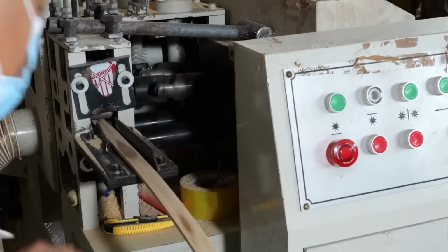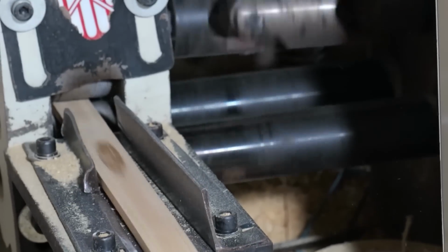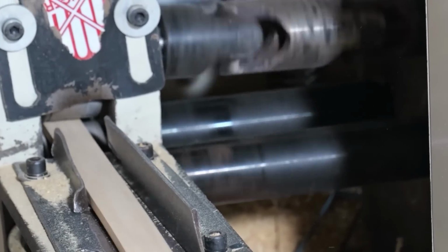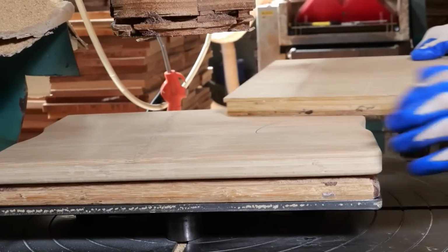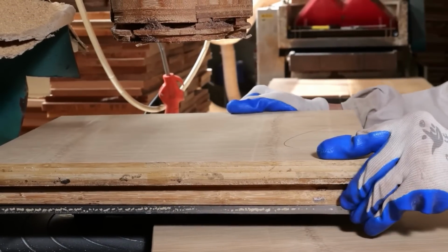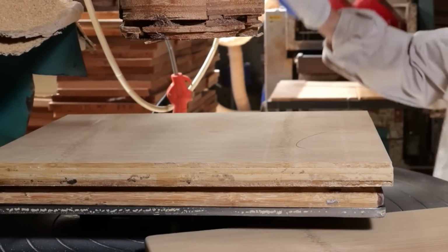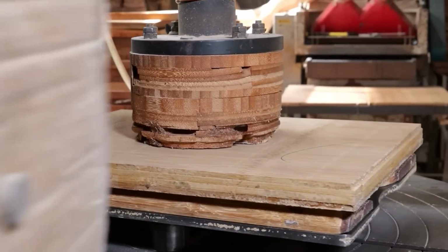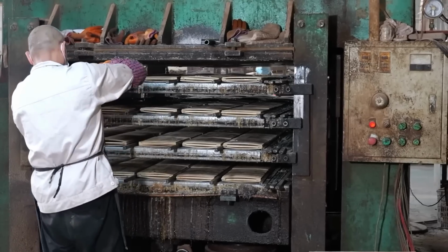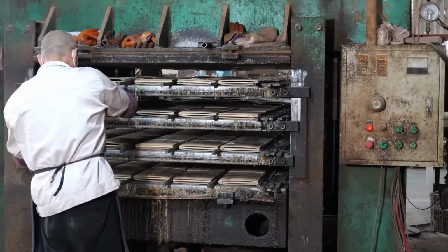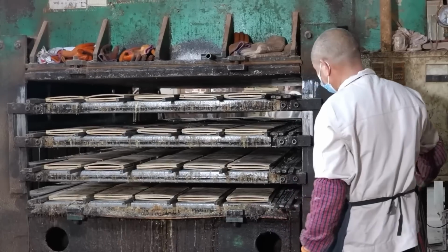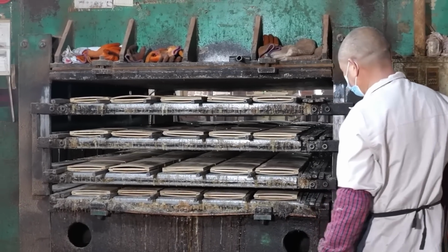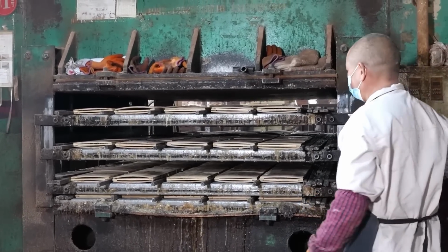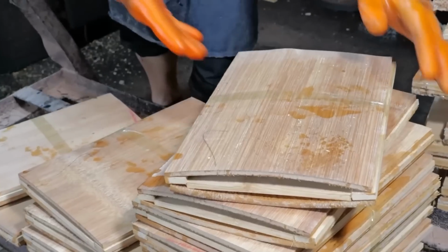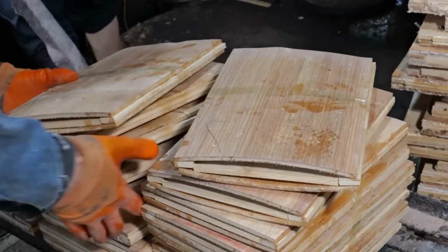The arranged strips then enter massive hydraulic presses, where temperatures reach 230 degrees Fahrenheit. Under pressures exceeding 3,500 pounds per square inch, the strips and adhesive fuse into solid panels. The precision this requires is extraordinary. Vary the temperature by just a few degrees, or the pressure by a small percentage, and the entire batch might be compromised.